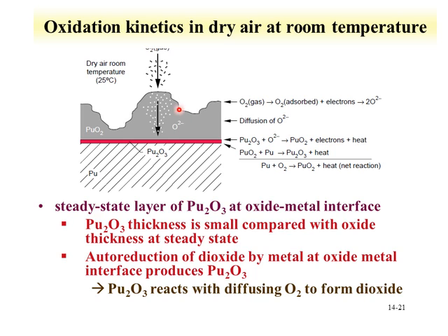The kinetics of this system vary slightly from the overall picture, where a thin layer of the trivalent plutonium oxide forms. Here we see what we discussed in the previous slide, this O2 reacting with the plutonium forming the dioxide, O2 penetrating, and then we get this small layer of Pu2O3, and autoreduction occurs where the plutonium tetravalent state reacts with the plutonium metal. You oxidize some of this metal to this trivalent state. And eventually, the oxygen that diffuses through interacts with this Pu2O3, forming the PuO2 state. As we see here, this layer is involved in the kinetics of the formation of this oxide.